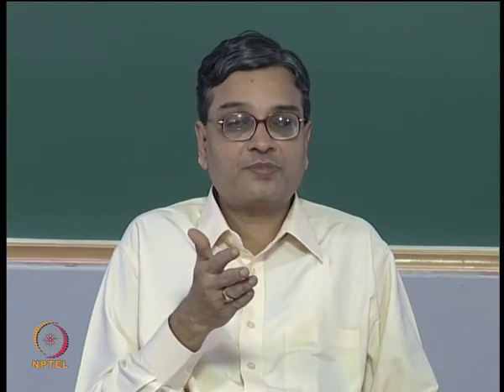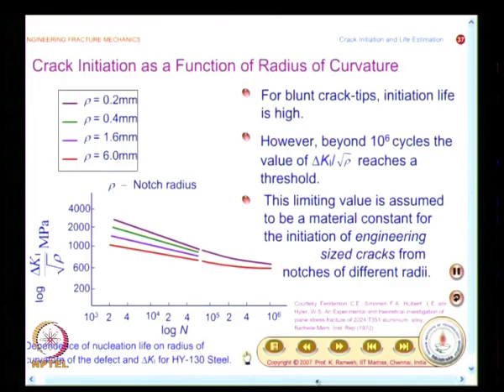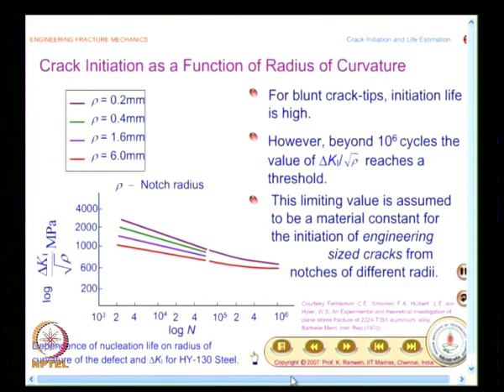So, people have coined several terminologies. You have fracture toughness, you have initiation fracture toughness, and there is a threshold value which is found to be a material constant. And this graph is for HY-130 steel. It shows the dependence of nucleation life on radius of curvature of the defect and delta K 1.